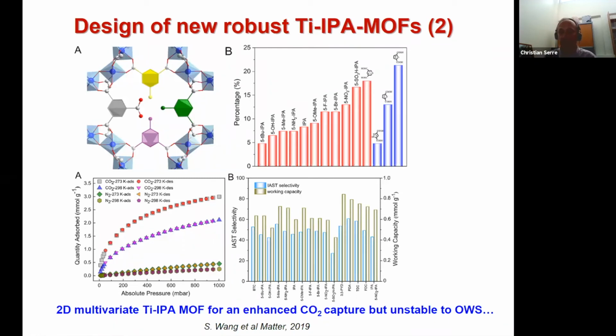But unfortunately, when our colleagues from ITQ tried the photocatalytic properties of this MOF, it was unstable and with a lot of gas emission. Their interpretation and ours is that this material suffers from too high a reactivity because of these terminal acetates in large number, which make the building unit too reactive, and therefore not stable enough under the conditions.